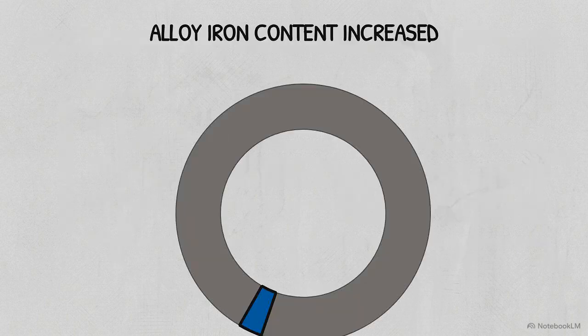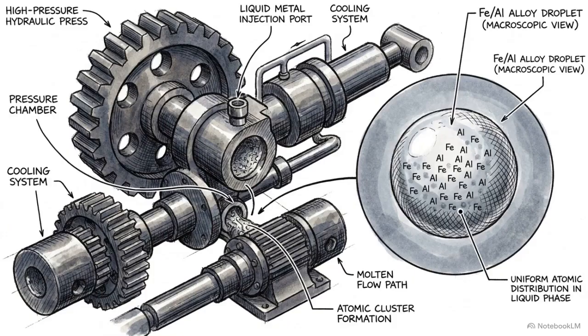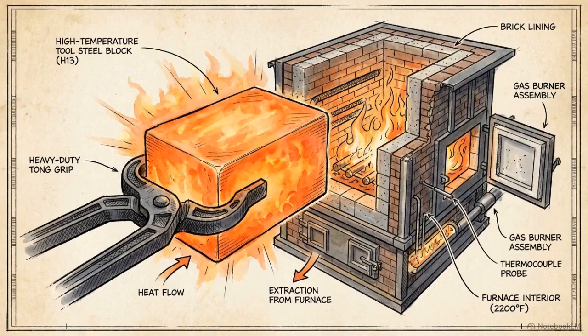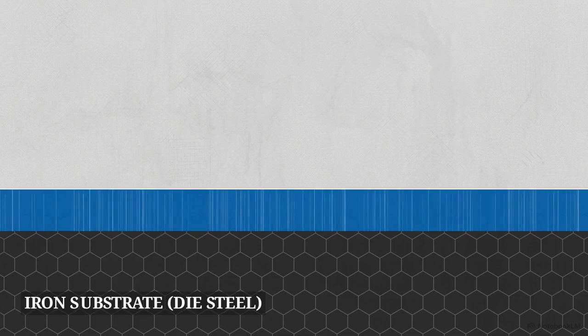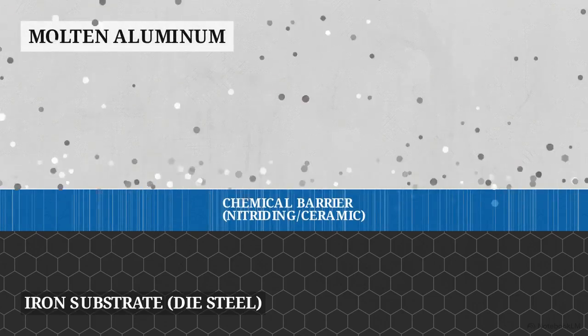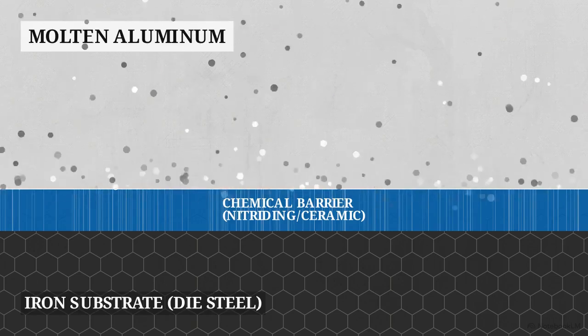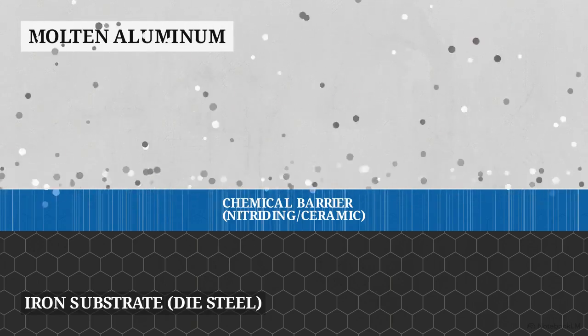Next is a specific metallurgical countermeasure, intentionally increasing the iron content of the aluminum alloy before it is ever injected. By pre-loading the alloy with iron, you satisfy its chemical affinity up front, nullifying its need to steal iron atoms from the die wall. The mold itself requires rigorous surface engineering defenses, beginning with the baseline requirement of using high-quality, properly heat-treated H13 tool steel. Engineers can then apply advanced chemical barriers, like nitriding or applied ceramic die coatings. This creates a distinct barrier layer that physically blocks the aggressive molten aluminum from ever contacting the iron substrate below.